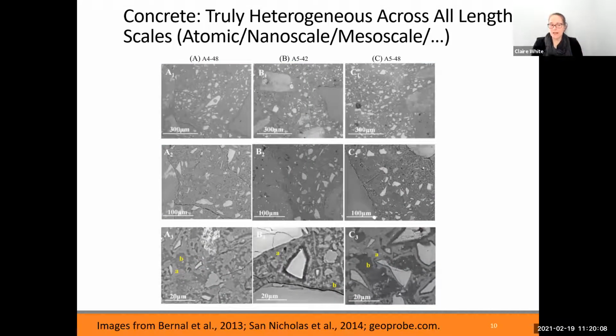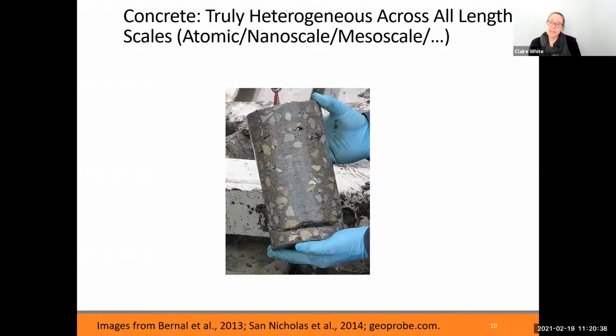If you look at about 100 microns or so, you can see the type of microstructure that forms where you've got partially reacted particles embedded in the matrix. And there's different kind of reaction fronts that have formed when the particles have been dissolving and the matrix type gel has precipitated out. You end up with some of these rings that form around some of the particles in the slag system, and people are studying why they form and what does that really mean about the reaction processes. And you can go to more of a macroscopic length scale, and then you've got interactions between rocks and sand and the paste itself.